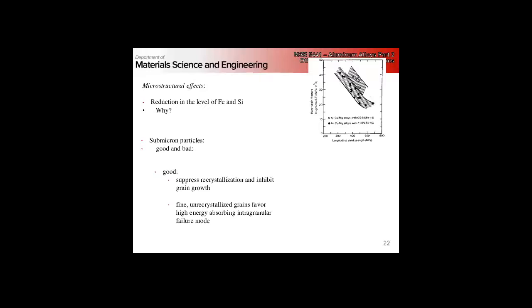Okay, submicron particles, as I said before, are the ones that suppress recrystallization and inhibit grain growth by pinning. Remember, the mechanism of that is the particles are on the grain boundary, and they have a lower surface energy than the grain boundary surface energy. So the boundary wants to stay right there, because now I've got aluminum and aluminum touching this low energy surface. Instead, if I move the particle off, now I have a higher energy grain boundary interface.